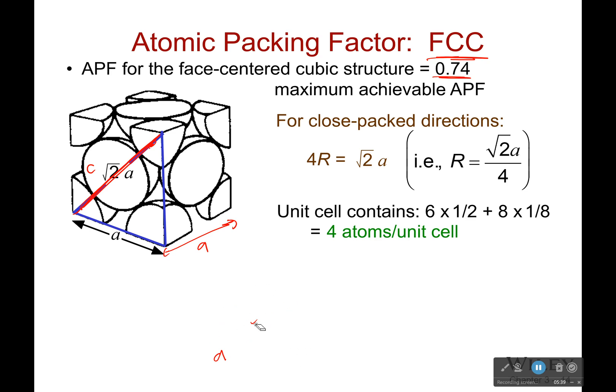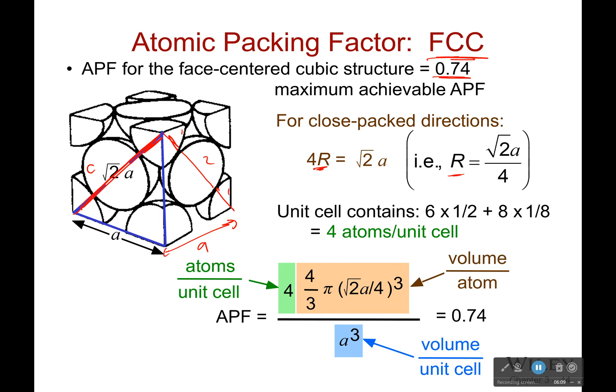Now, we also know that that is four radiuses. We have one radius right here. I'll go over this strictly: one plus two plus one. So one, two, one makes four radiuses. And therefore we can get our radius in terms of a. We're doing this because we know what the volume of a sphere is. It's four thirds pi r cubed. And so we're going to plug in now instead of having r in there, we're going to put it in terms of a.